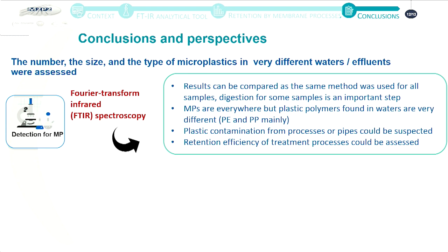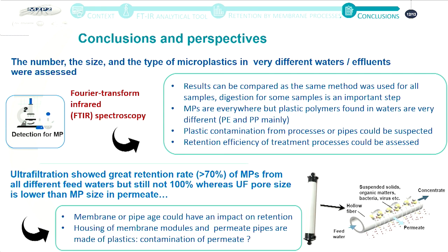So in conclusion, we could assess the number, the size and the type of microplastic in very different waters: freshwater, seawater and wastewater. We could see that plastic contamination from processes or pipes could be suspected. We could assess the retention efficiency of different treatment processes, with a focus on ultrafiltration, which showed a great retention rate for all the different treatment lines, but we still do not reach 100% as expected.